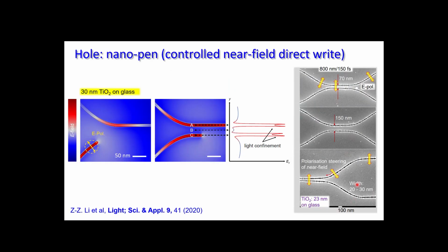And here are examples. So you're writing nano grooves, and you can write them quite closely. Certainly the edges show some structure, so you definitely melt material. At the same time, you can also appreciate that because material is removed and not a lot of it should be removed, there is no field of debris. So you really write nano features in your resist with nano-scale precision and definition.